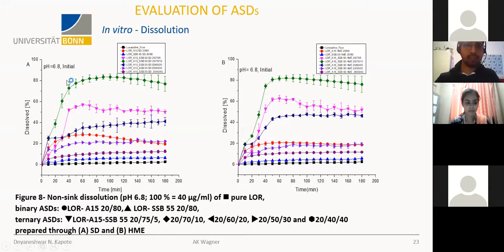The green one is our 20-70-10 percentage, where we observed 80% of the API dissolved, compared to 2%. So this indicates that the solubility is enhanced and the supersaturation is also maintained.